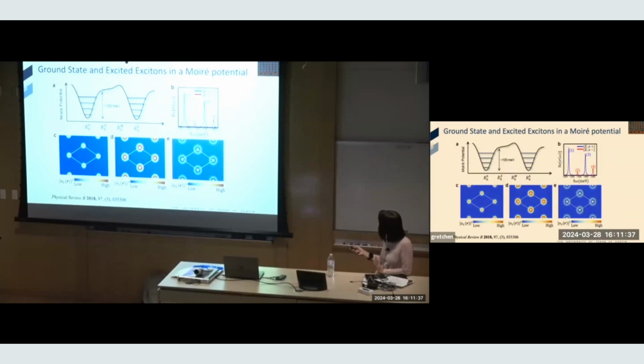It turns out there's another explanation why you can have this alternating selection rule. These Moiré potentials are kind of deep. So if you solve a square well problem in quantum mechanics, you can have not only the ground state, but excited states. It turns out these ground and excited states have different center-of-mass wave functions, and they also follow different selection rules. So there are really multiple ways that you can have multiple exciton resonances following different selection rules. We chose this picture in our published work, partially because we see the higher energy peaks disappearing faster with temperature. They have shorter lifetime, which just indicates maybe they're higher energy states. So that's the picture we picked.